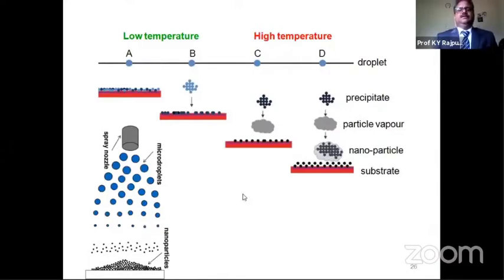So the temperature of fabrication is also very important. You cannot deposit the film at every temperature. It should be optimum, such that the energy required for pyrolytic decomposition and subsequent recrystallization of the material is suitable. So it should neither be on the higher side nor on the lower side. Here I have schematically represented the various stages through which the aerosol reaches the hot substrate while forming the deposits on the substrate.